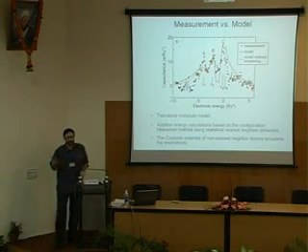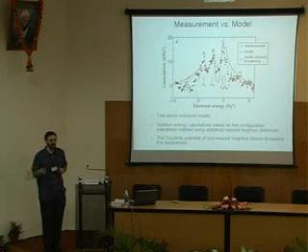Here are my black dots, peaks A, B, and C. This careful treatment looking at the configuration interaction calculation, plus all these effects that smear things out, tends to give you this funny structure: electron number 1, electron number 2, electron 3, and 4. Massive approximations were put into generating this theory. The effective mass approximation, or the Luttinger-Kohn approximation in the first place, our treatment of these nearest neighbors, many things were simplified. Yet amazingly, we still get some qualitative agreement between the two.